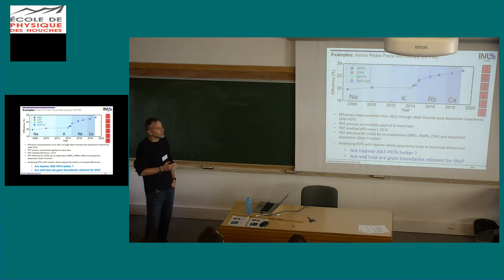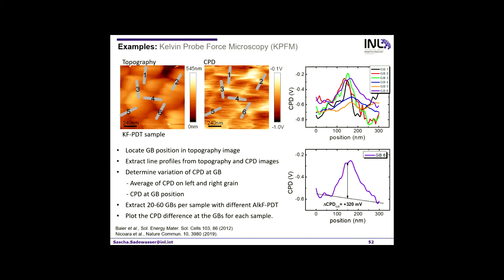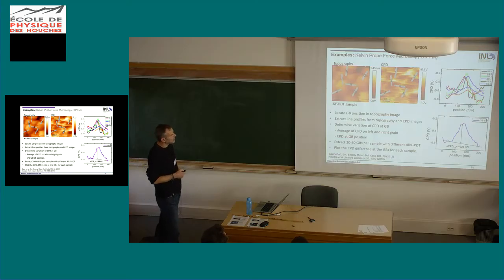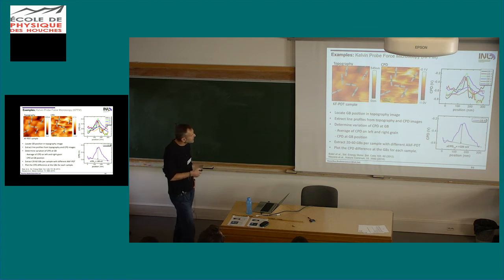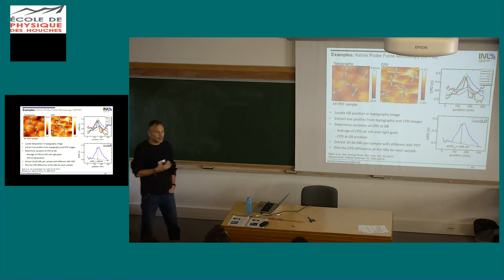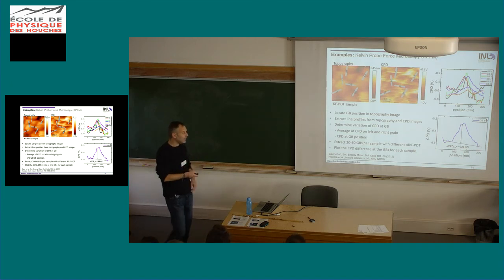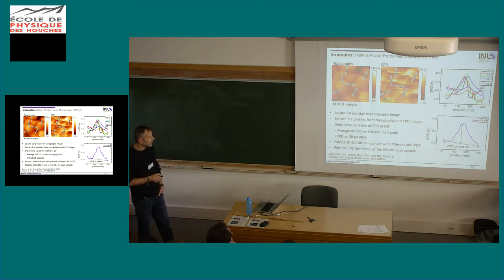So it is fairly well known that alkalis tend to accumulate at grain boundaries. So we wanted to see if we can see something in our method. So this was part of a European project where we collaborated with ZSW, so we had access to very good samples. And again, we imaged the topography, we imaged our work function image, and now you can already see here our grain boundaries suddenly are bright. So instead of going down, now we actually see an upward change of the contact potential difference.